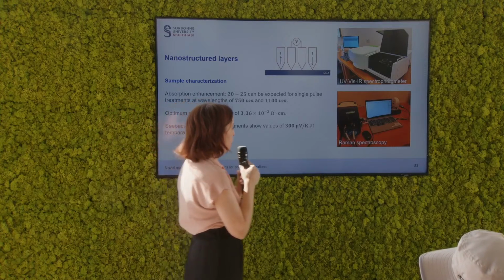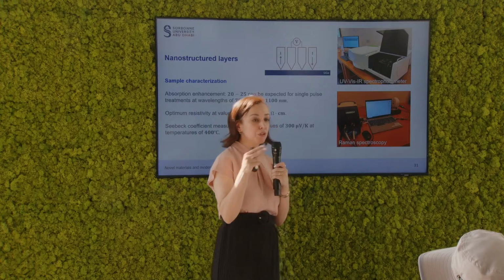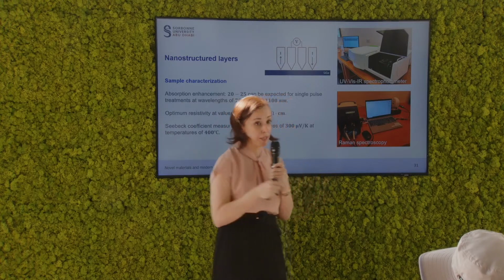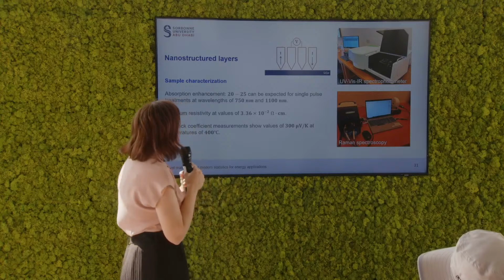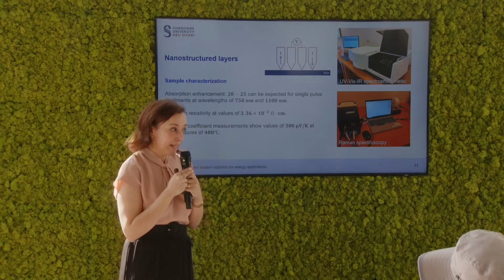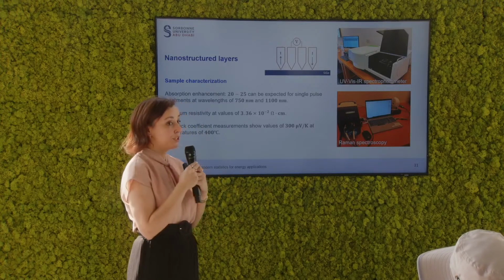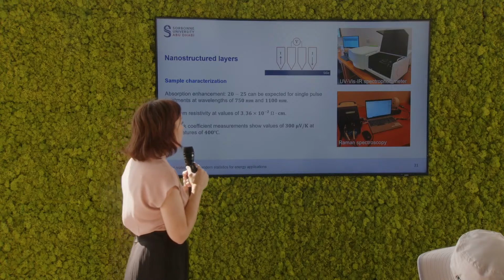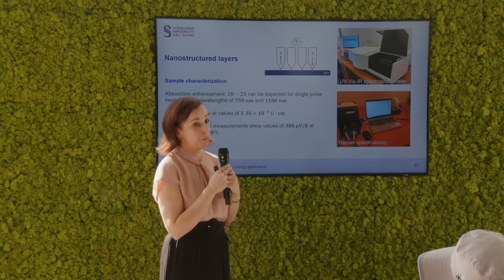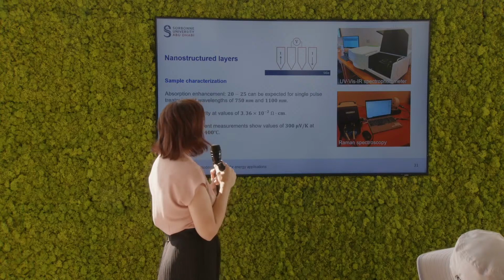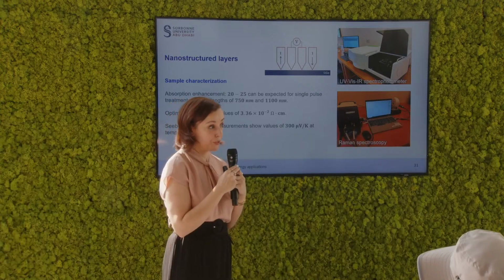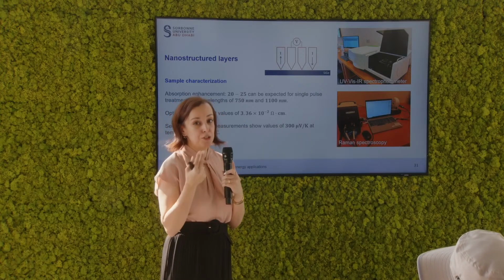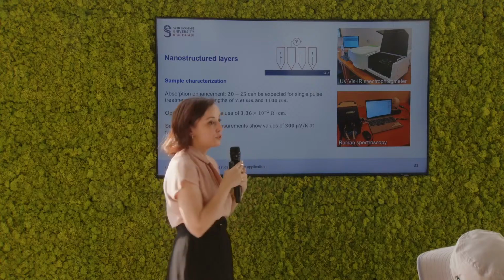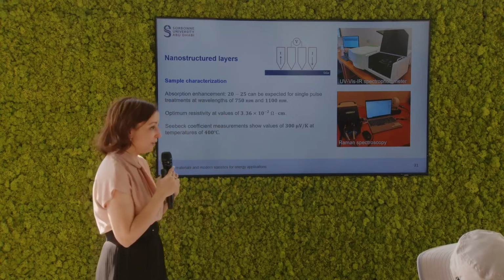We also confirmed the change from amorphous to polycrystallinity using Raman spectroscopy as well. In terms of thermoelectric behavior, Seebeck coefficient measurements that were conducted show values of around 300 microvolts per Kelvin at temperatures of 400 degrees Celsius. So in terms of recent research, these values surpass the reported values.